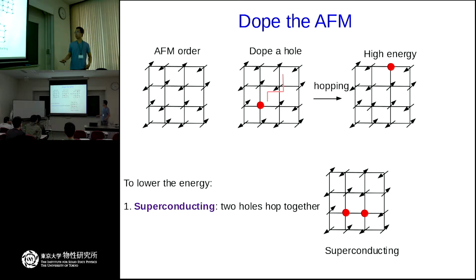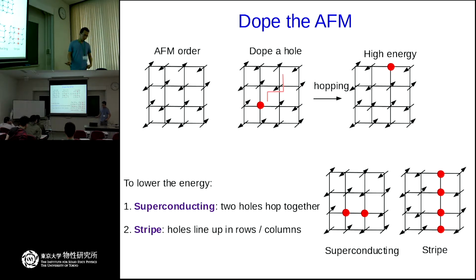We can think of two ways to lower the energy. The first one is the so-called superconducting state. If two holes hop together, then there will be no frustration, as shown here. The other way is the so-called stripe state. In the stripe state, the holes align in a line like this. The hole can hop in the river of holes without destroying the antiferromagnetic background. So these are two possible consequences if we dope the Néel order. Of course, this is just some hand-waving arguments.